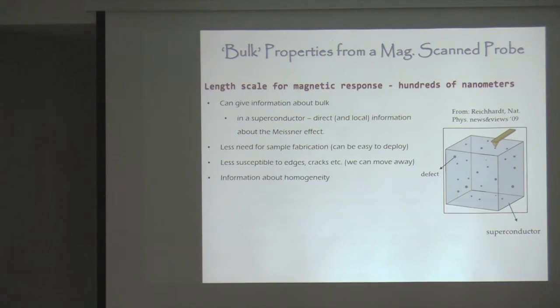We use a local probe, and that's a spatially resolved probe, and that's really useful because you can move this thing around. So you get a sample. We don't have to do a lot of device fabrication. We can just find a clean area on the sample, bring the tip to the sample, get a measurement of the penetration depth, go to a different point, and do this again. That's very, very convenient. We can move away from all kinds of inhomogeneities, cracks, edges. These are all problems in measurements where you have to measure the whole sample. So that's really nice.